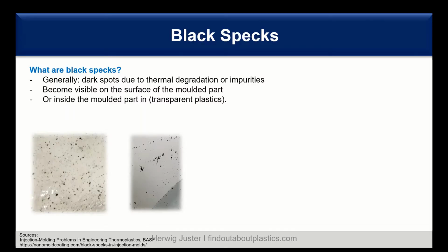First, to start with, what are black specks? So in general, black specks are dark spots due to thermal degradation of the material or impurities, and they become visible on the surface of your molded part or inside the molded part in case you have transparent plastic. So you can see here some transparent polycarbonate parts which have these small little black spots everywhere, which looks like stracciatella, as we also say, and this needs to be avoided.